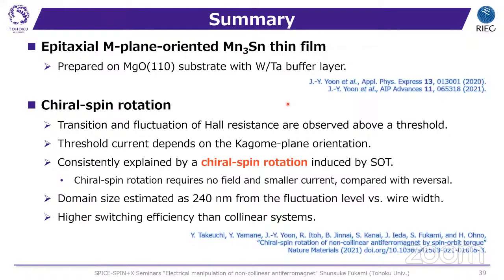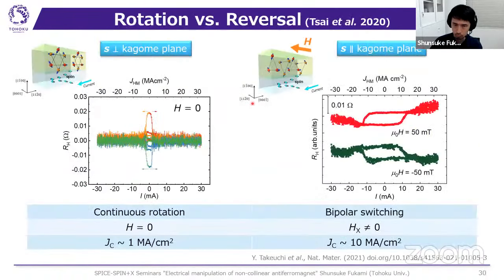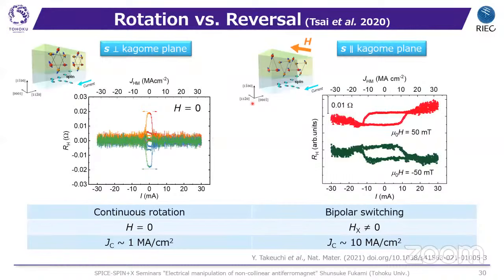Thanks a lot for this interesting talk, and I'm very happy that experimentalists can realize this. It's fantastic. What I learned from the ferromagnetic spin-induced dynamics is that there is a hysteresis in the threshold currents when you go up and down. So the threshold current for starting rotations is larger than the current for stopping rotations. At least this is predicted by theory for collinear antiferromagnets. So have you tried or have you seen this kind of hysteresis?